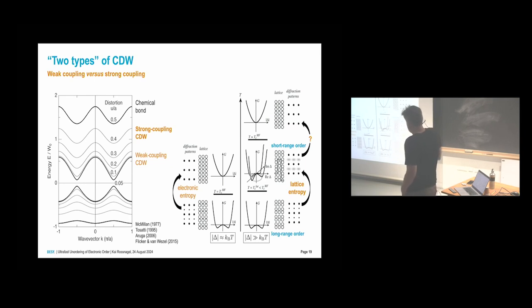In a weak coupling charge density wave, the gap is small, and that means if you raise the temperature, you can have electronic excitations across the gap, and this leads to electronic entropy, and electronic entropy then drives the transition to the normal state. In a strong coupling charge density wave, the gap is much larger than the thermal energy, so you cannot excite electrons across the gap. Instead, you excite phonons, and the lattice entropy drives the transition, and this transition then happens in two steps.